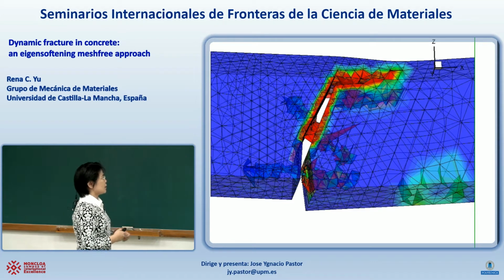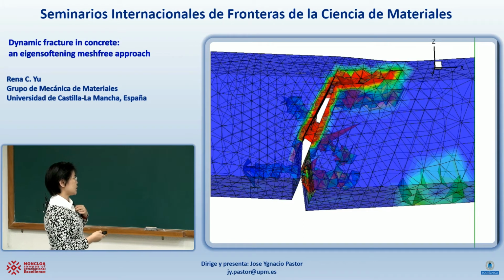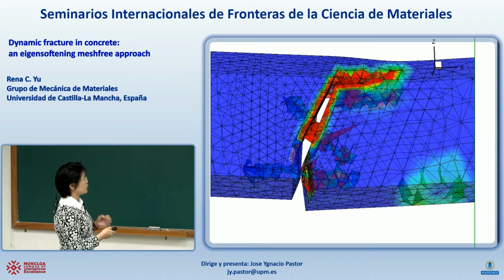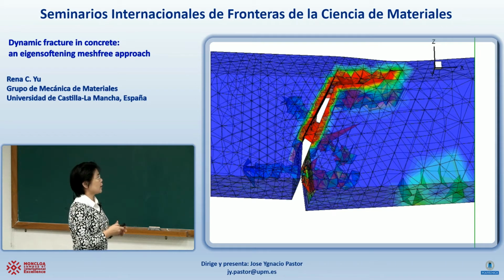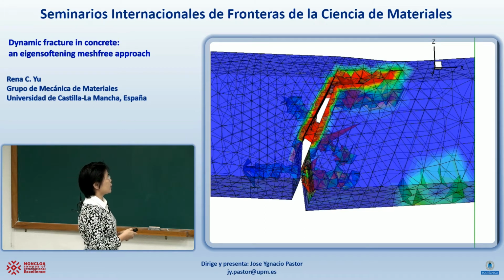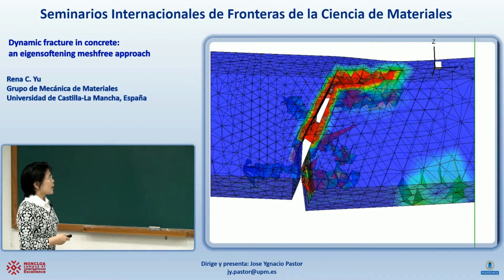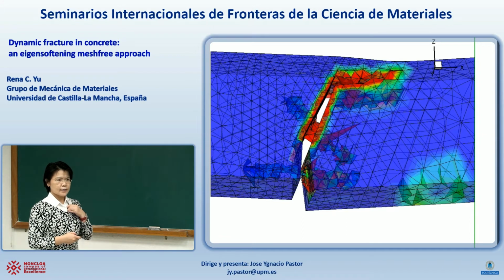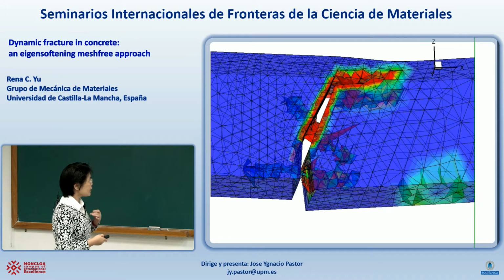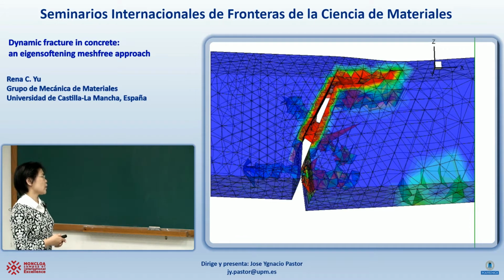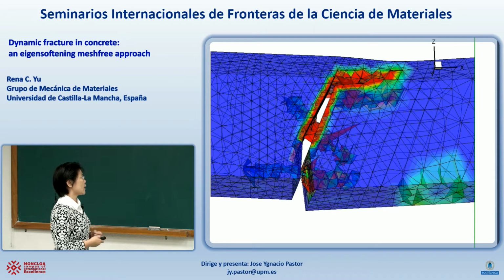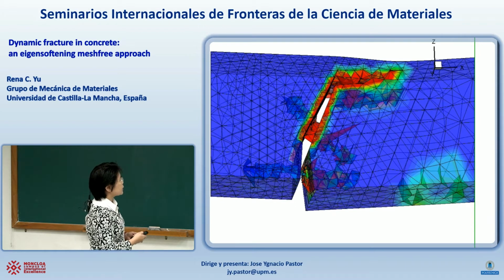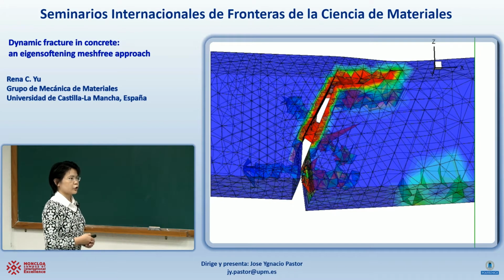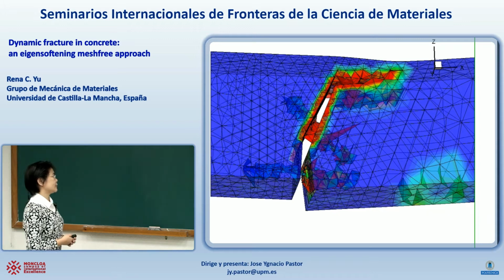I have to say this is a nice video, but see here, it goes along the element boundaries, but here, since the predicted crack does not exactly align with the element boundaries, it becomes zigzag. Okay? This simulation was actually a static test, but we had to implement a quite complicated static-dynamic algorithm to predict this part, which is a dynamic fracture within a static loading.